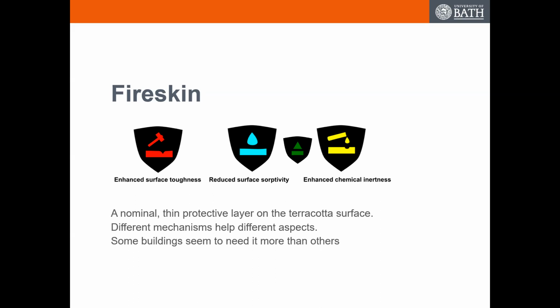As far as we can work out, it's because it was a particular clay blend that was fired to a good temperature for a decent time. And so all the way through, the cross-section was well developed. And the cross-section, even at the middle, might be stronger than the fireskin on some of the blocks that were coming out in the early manufacturing, where we just whacked it in the oven for one day.